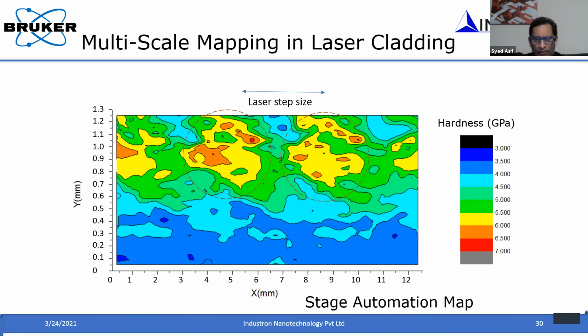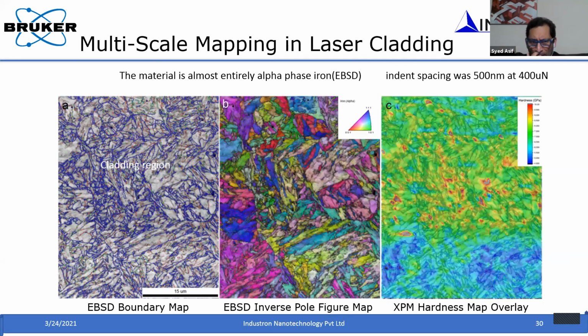And you can also, depending upon the laser step size, see these domains pretty clearly. So this is how you can do an array of indents, but this is still a macro scale. Now, if you go to a much smaller scale, you can still do it with this mapping technique. In this particular case, the last image here is the hardness map, and this map was constructed by doing experiments with a spacing of about 500 nanometers between indents.